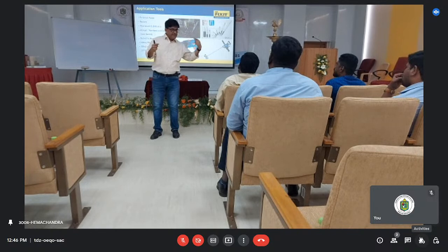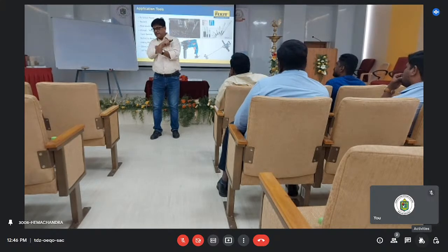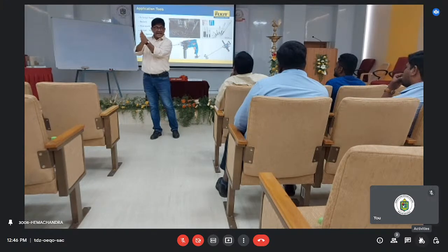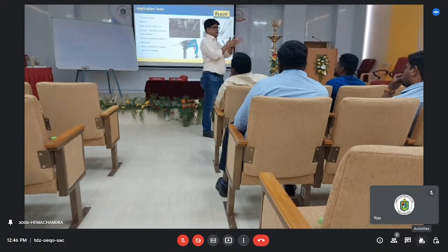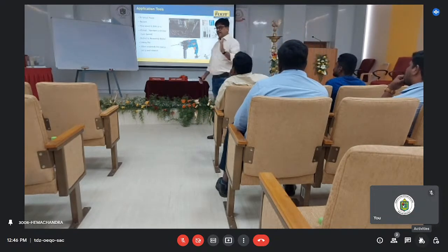So that when I am putting the pressure, my material is leaving from the 1/4 distance of the source, and then immediately hits the source at the base point, right? And it is blocking at the source level. It should be blocked at the source level, not at the middle. Am I clear? So that is why that drilling is important.